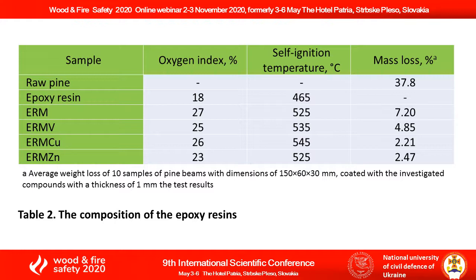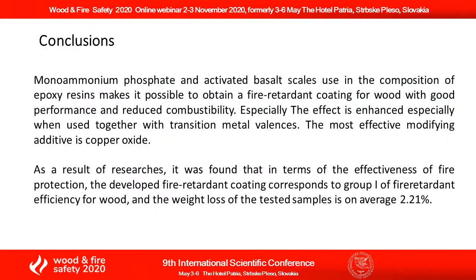Comparison with similar coatings applicable for wood fire protection allows us to state the effectiveness of the use of transition metal valence oxides in combination with ABS and MAP for epoxy compositions. The data in Table 2 show that according to the efficiency of increasing the self-ignition temperature of the epoxy composition ERM, transition metal oxides can be arranged in the following sequence: zinc oxide, vanadium oxide, copper oxide.